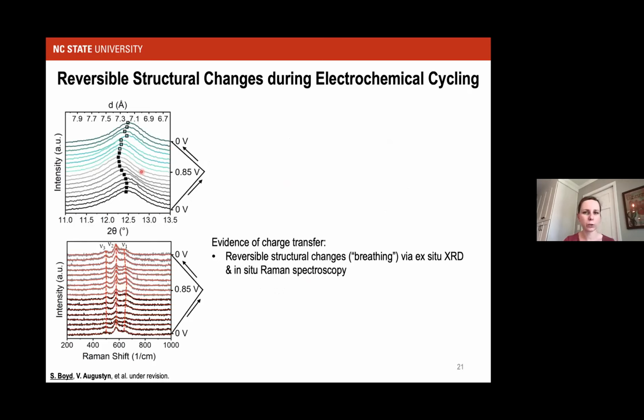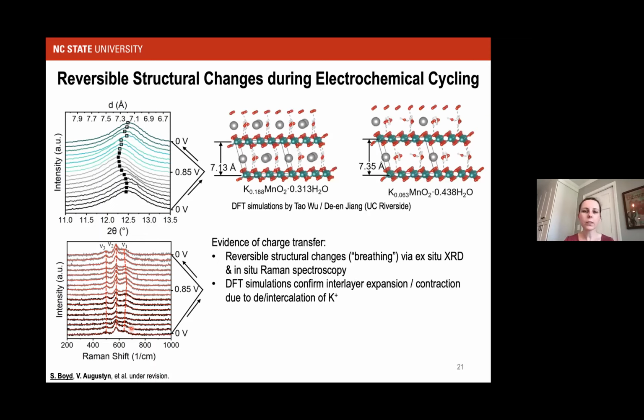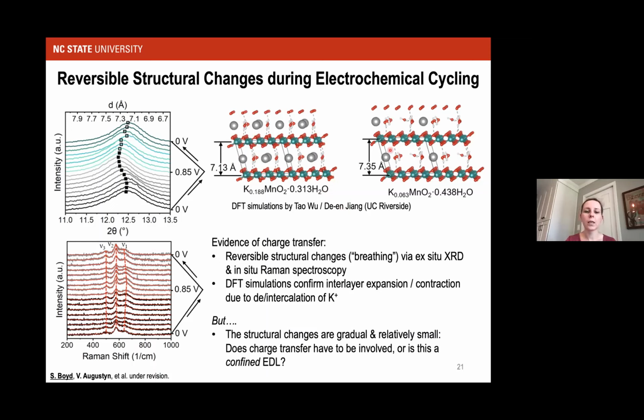We see evidence of reversible structural changes from ex situ X-ray diffraction as a function of applied potential, as well as in situ Raman spectroscopy that are showing that the solid state structure is flexing or breathing, if you will. And that suggests that you have an intercalation mechanism taking place, which many of us would consider evidence of charge transfer. And from the density functional theory simulations, these are done by Tao Wu and De-en Jiang's group at UC Riverside, we do indeed see that, when the potassium ions deinsert from the structure, this interlayer spacing will expand. However, these changes are gradual and relatively small.